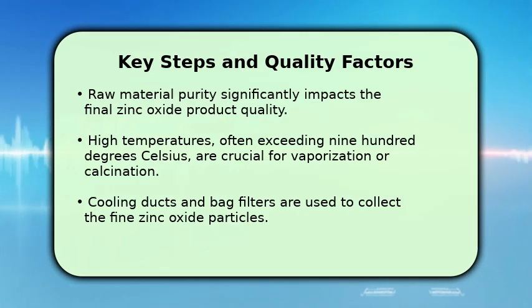After formation, the fine zinc oxide particles are typically transported through cooling ducts and collected using specialized bag filters. The specific process conditions also dictate the particle size and shape, which can range from 0.1 to 10 micrometers.